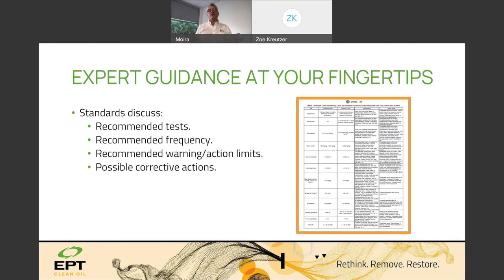I'm sort of giving you all my secrets here today, but when I go to a plant in any country and they're having problems with an application, I'll always go back to what does ASTM say for this application, and then I'll compare the lubricant analysis being done at site to that standard, and I will tell them you're not testing for these 3 or 4 additional things. You need to test those additional things. You need to interpret them according to these guidelines, and we can help you then achieve those.